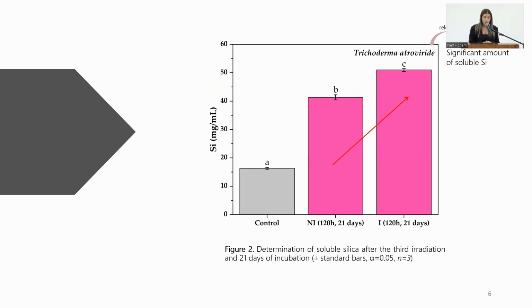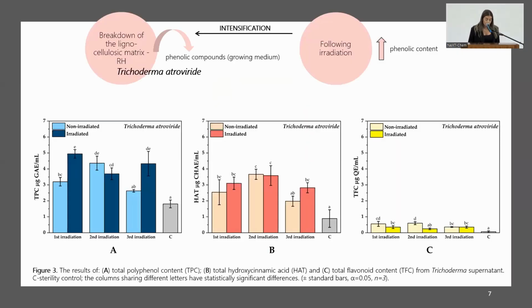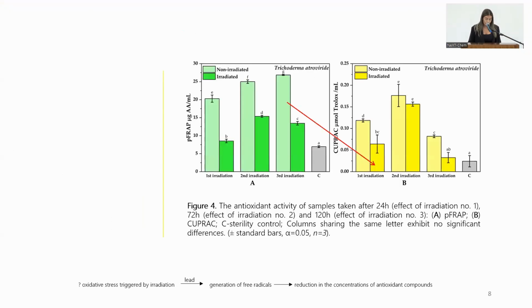The soluble silica from the culture was determined at the end of the experiment. Figure 2 shows that Trichoderma atroviride released a significant amount of soluble silica from rice husk, in both the irradiated and non-irradiated samples. The soluble silica in the culture media was increased after 3 irradiations compared to the non-irradiated one. The polyphenolic content had a heterogeneous behavior. As we mentioned before, Trichoderma atroviride is involved in the breakdown of the lignocellulosic matrix from rice husk, leading to the release of phenolic compounds into the growing medium, and the increase in phenolic content following irradiation shows an intensification of the breakdown process.